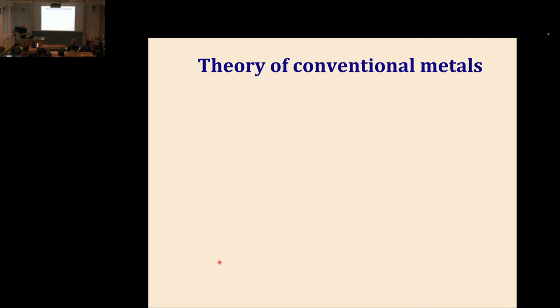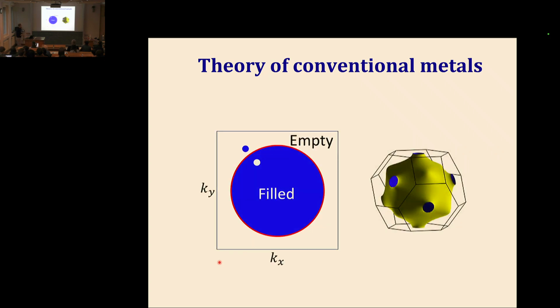Before we talk about strange metals, let me briefly reiterate what Michael said about what conventional metals are. One of the most successful theories we have in condensed matter physics is Fermi liquid theory. The idea, as was explained, is that we have electrons moving in a periodic potential and interacting with each other. This interaction is not weak by any means. Usually it's very strong. Nevertheless, the astonishing fact is that we can treat excitations close to the Fermi surface at very low energies as if they were non-interacting particles with a modified dispersion.